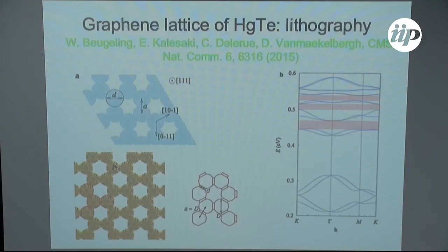You could also pattern, for instance, cylinders in MBE. You could grow it with cylinders which are truncated. It's very important to truncate because they have to connect through large surfaces, okay? Or you could grow spheres which are connected via cylinders. The fine details would change. In this case, for instance, you get a stronger Rashba that splits your spin up and down levels, but you will still get these topological gaps that are quite large, okay? So it doesn't depend on the details of the structure, but it's just by creating holes inside our structure.